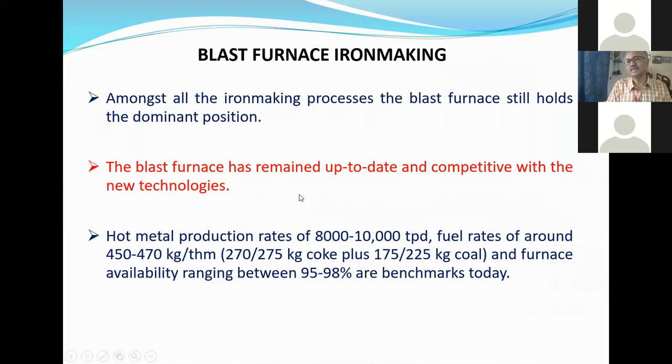As I said, in the SR technology, the major problem is that of gas utilization. And the blast furnace is a very, very energy efficient process. Its exit gas goes around 150 degrees centigrade, and whatever CO is there, you can use 30% in the blast furnace stove itself, and 60% for downstream application. It is well established. But in the case of the SR process, the exit gas contains a lot of CO, and you have to utilize it, otherwise it may not be competitive with the blast furnace technology. Okay, so that is the thing.